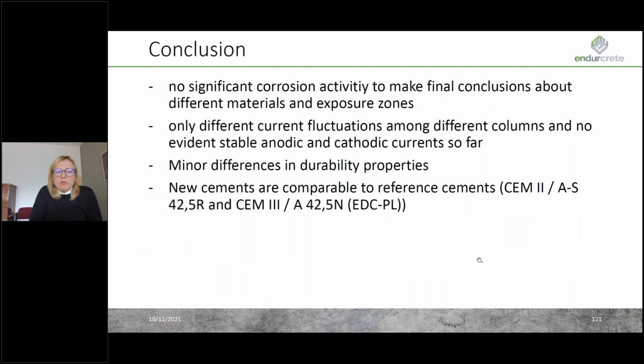So what we can conclude, there is no significant corrosion activity to make final conclusions about different materials and exposure zones. Only different current fluctuations among different columns, as said, and no evidence of stable anodic and cathodic currents. Very minor differences in durability properties, and we can conclude that new cements are comparable to reference cements, which were CEM II AS 42.5R and CEM III 42.5N.